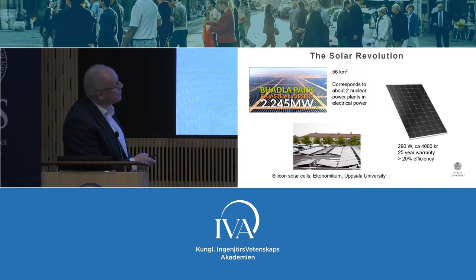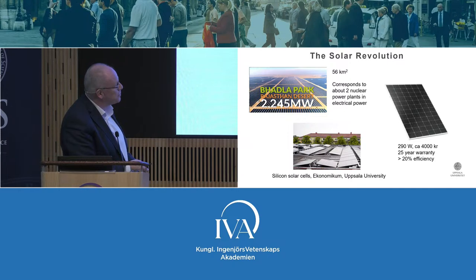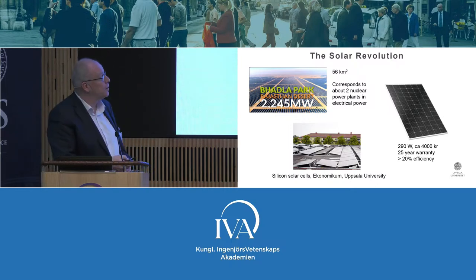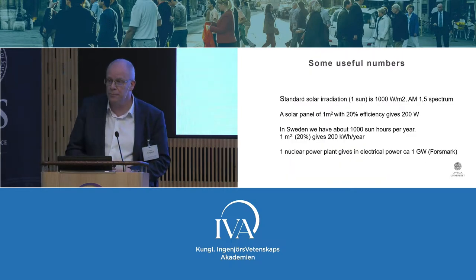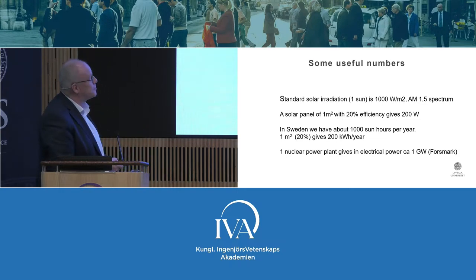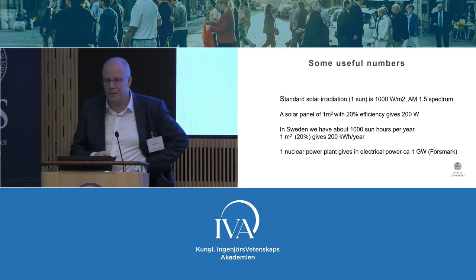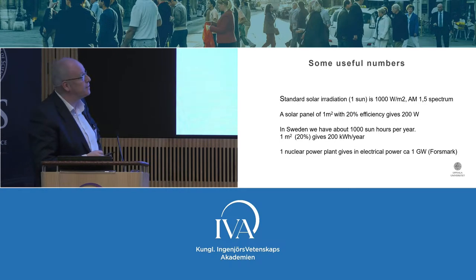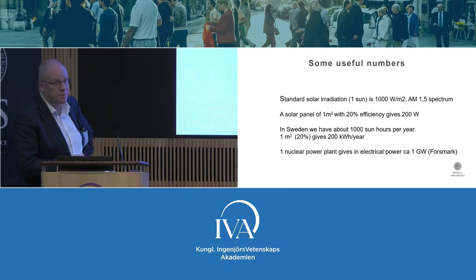And this, I found on the internet, if you want to buy a solar panel, costs about 4,000 crowns here in Sweden, and 25-year warranty and so on, 20% efficiency. So that is a little bit how it looked like. For those of you who think about installing solar cells, these are some, at least in Sweden, maybe useful numbers. We actually use the sun as a unit. We call it one sun when we have one light intensity of a sun. So it's standardized. It's 1,000 watt per square meter and with a specific spectrum, which we call AM 1.5. So that means if you have 20% efficiency, you get 200 watts from a square meter solar panel. And in Sweden, we have about 1,000 sun hours per year. So then you can calculate that this is 200 kilowatt hours per year from one square meter.